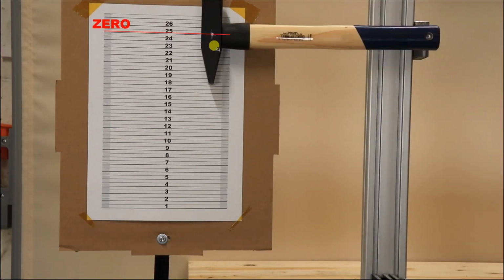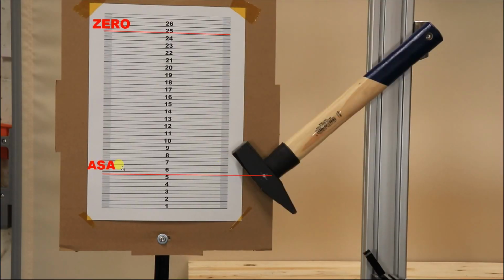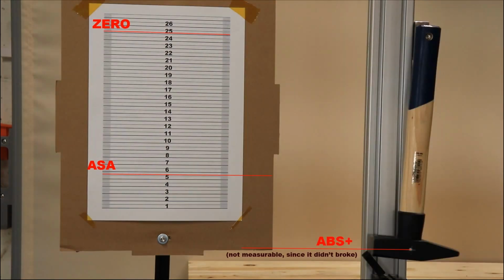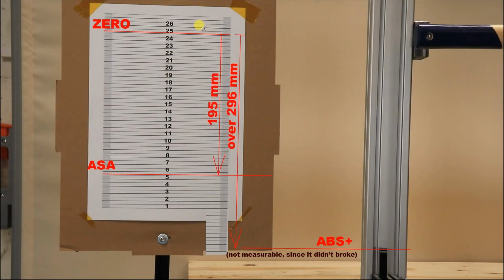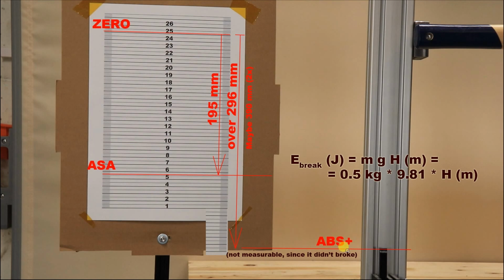This is the scale, and this is the 0 position of the hammer, and this is after breaking the ASA test specimen. And this is after breaking the ABS Plus test object, and don't forget, this is not really measurable because it didn't break. But approximately I can see it is very close, so yes, it is possible that it is twice as strong as the ASA. And if I measure everything from the 0 position, I can use these values to calculate the breaking energy. And to get some numbers for the ABS Plus, I will place it in a graph that it is really double the strength of the ASA.